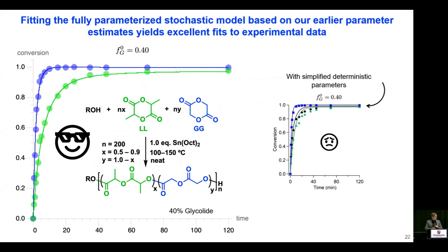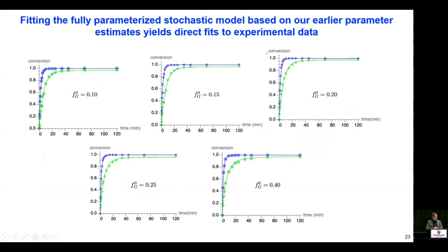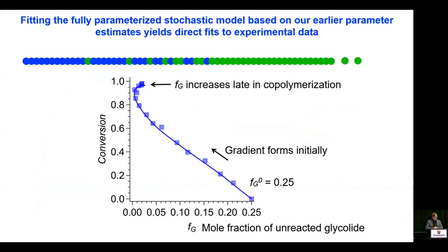And how does this work? Well, it works quite well, right? We can fit routinely to reversible copolymerizations with transesterifications. It gives us a nice description of the system. We vary the starting composition of glycolide, still capture everything here. And actually, this presents a picture of what's happening in this copolymerization.